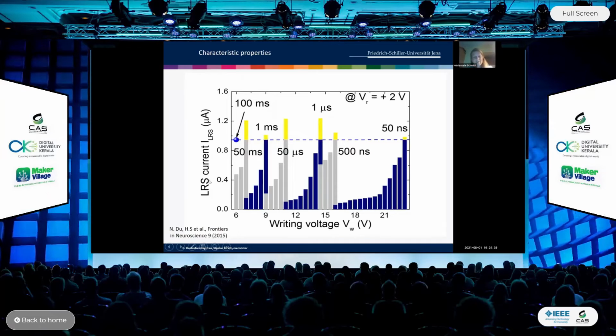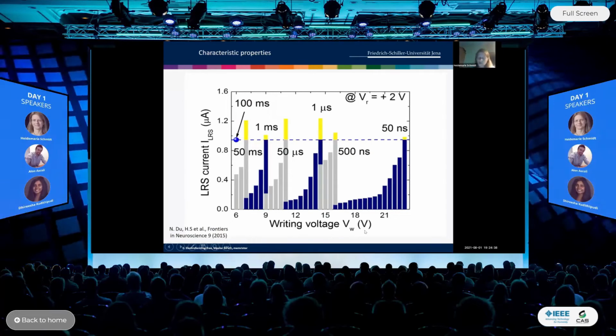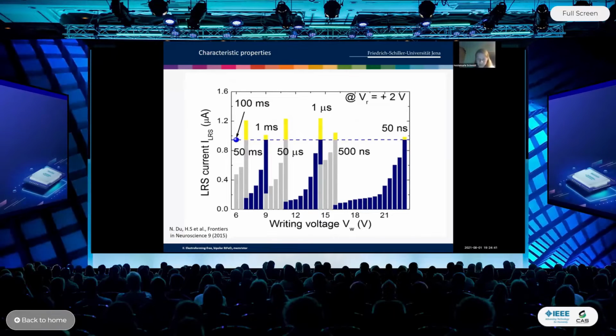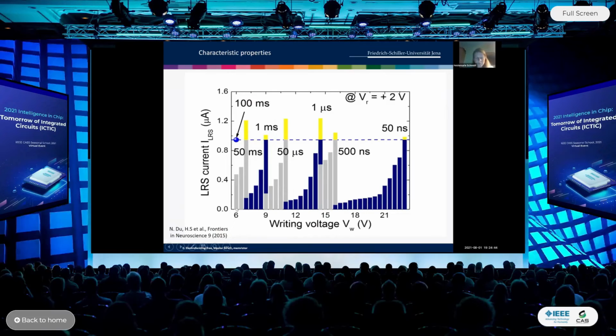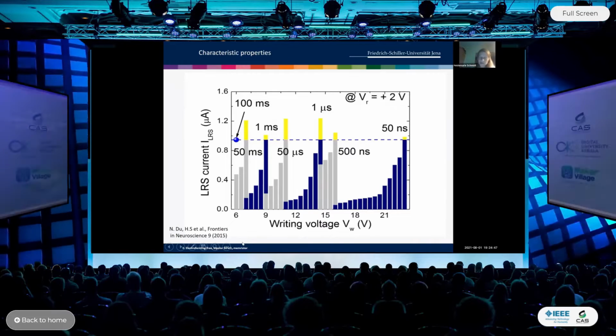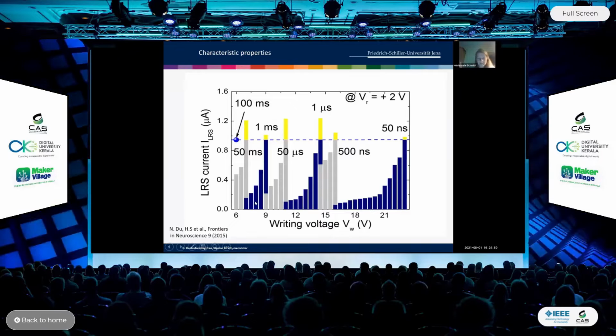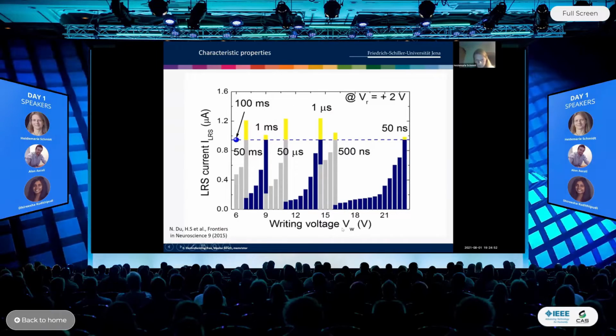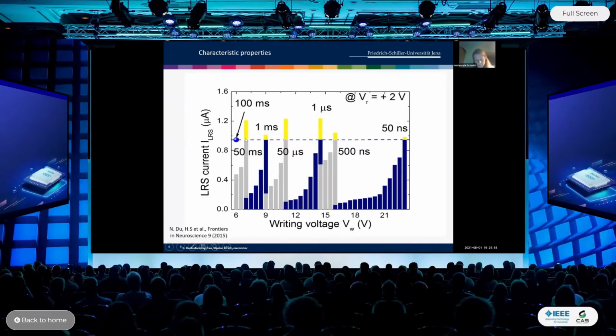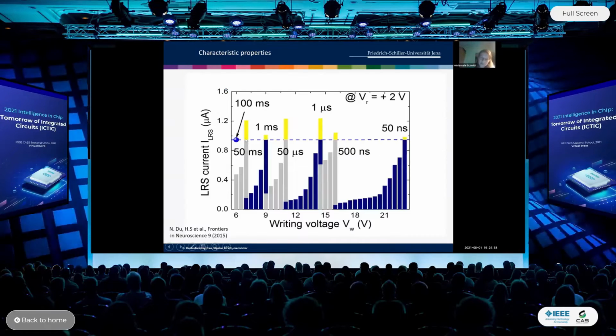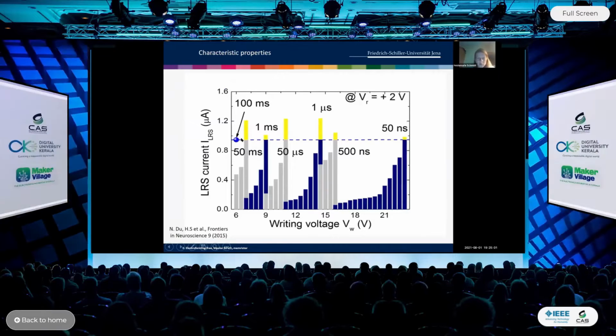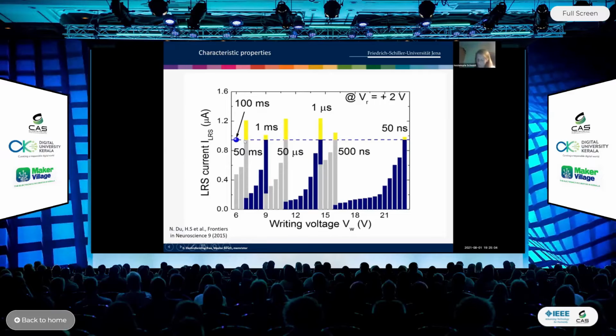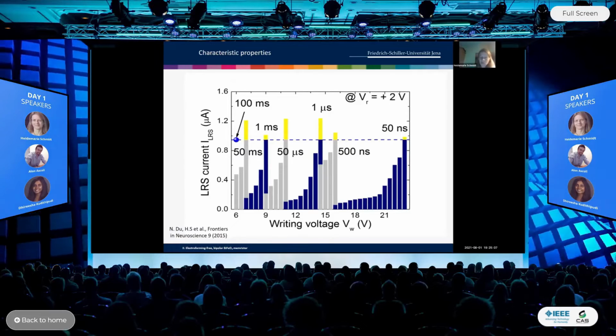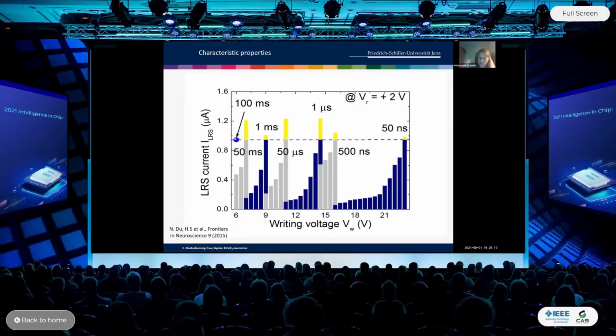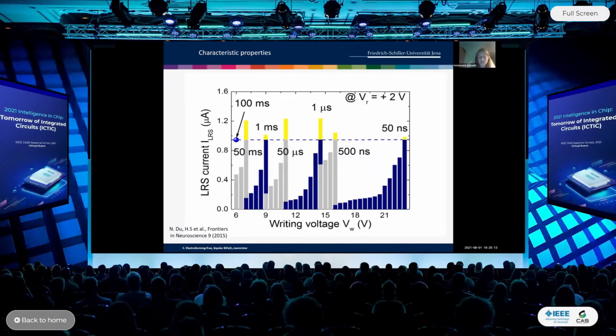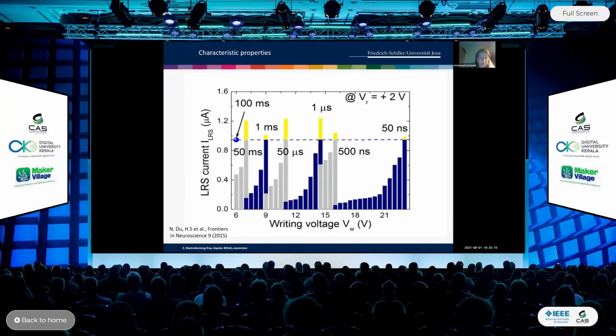What you can see here is the writing voltage. This is the amplitude of the rectangular bias we applied, in positive direction. And before each new experiment we always put the system into the higher resistance state. Then we successively increased the writing voltage amplitude and looked at when the system switched from the high to the low resistance state. It means, when was there enough time for the oxygen vacancies to drift from the top to the bottom electrode, to overcome the 300 up to 650 nanometer thickness of this bismuth iron oxide memristor.